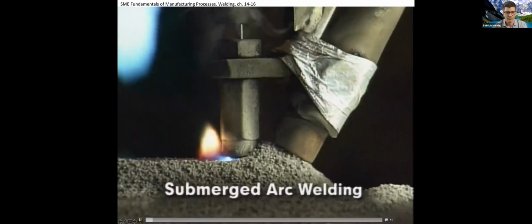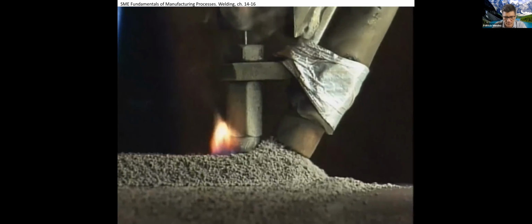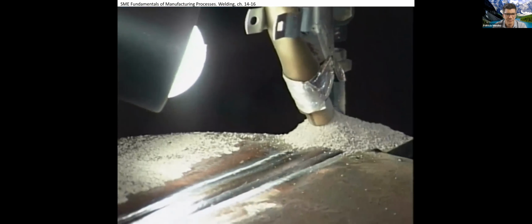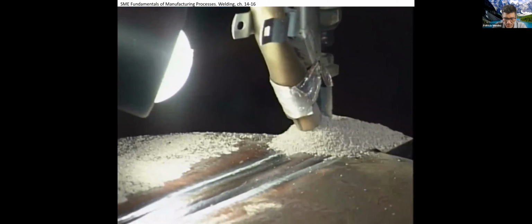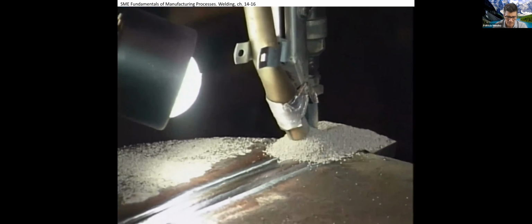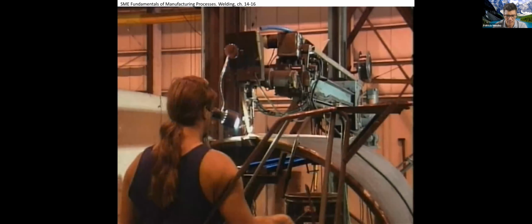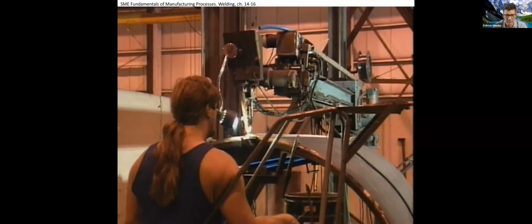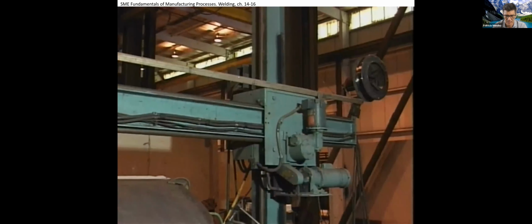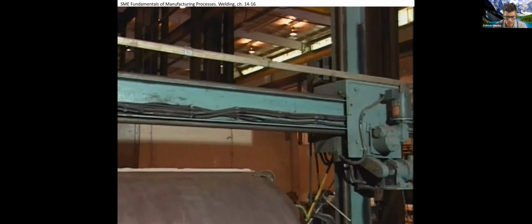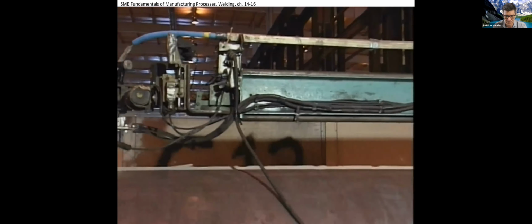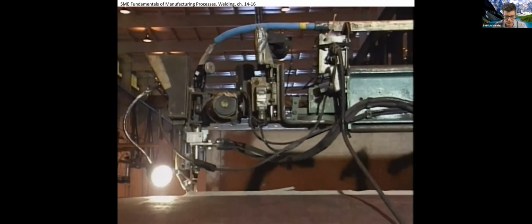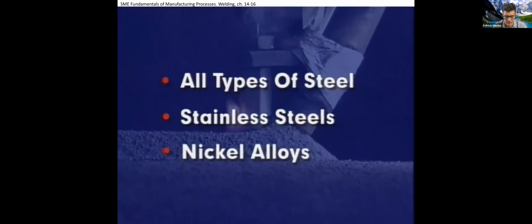In submerged arc welding, a bare, continuous consumable electrode wire, shielded by a layer of granular flux particles, sustains the arc. When the arc is struck, the tip of the electrode is submerged in the flux, and the arc is not visible. Welding proceeds without the intense radiation that characterizes open arc processes, and with little fumes. The submerged arc welding process varies from semi-automatic to fully automatic. Equipment includes automatic wire feed devices and joint tracking systems to move either the welding head or the workpiece. Submerged arc welding is commonly used to join all types of steel, stainless steels, and nickel alloys.